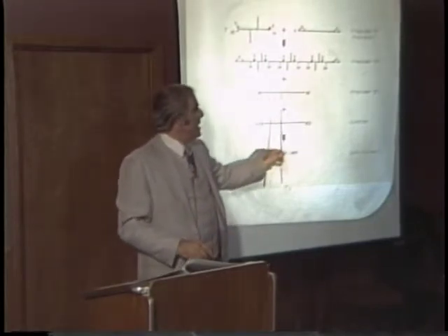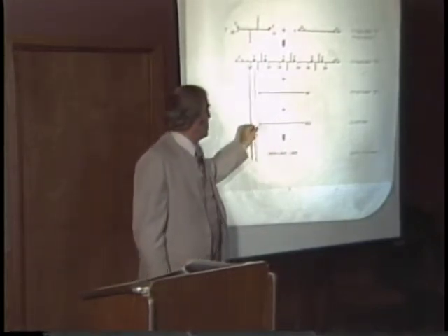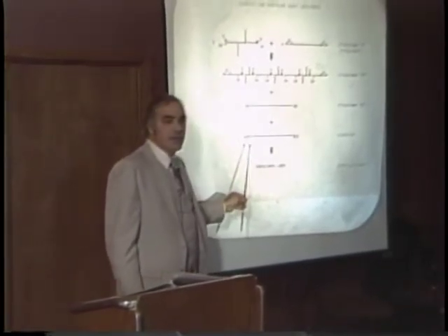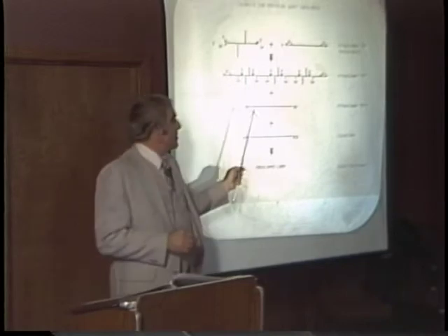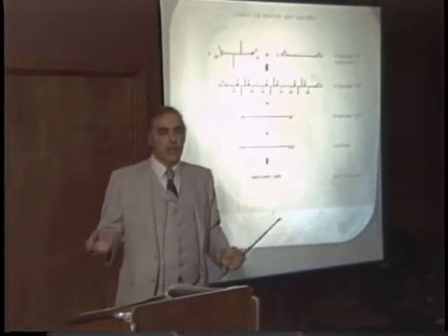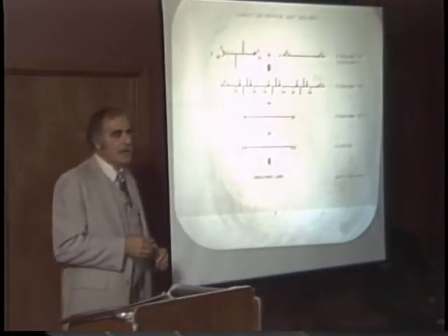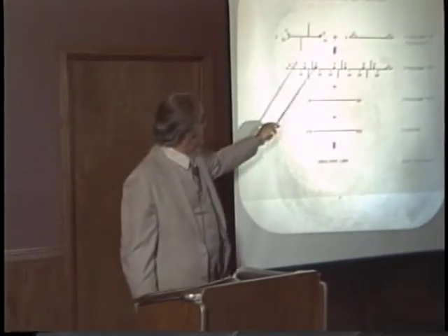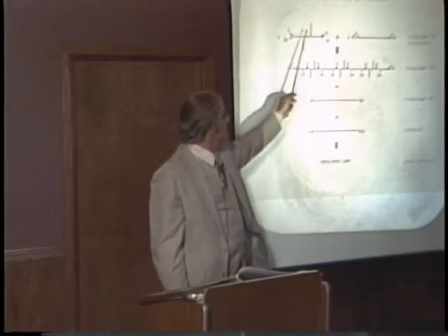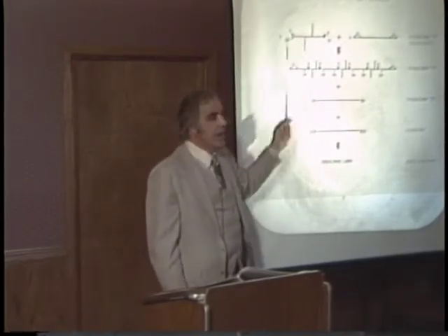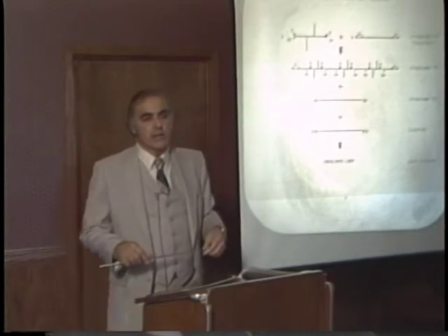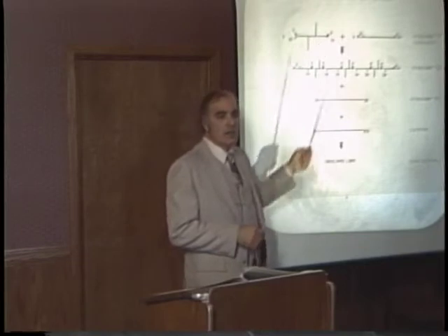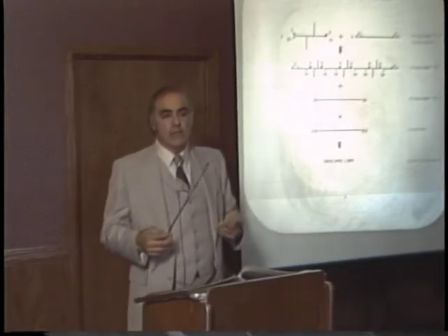But the next thing we do is we take another material and we graft it into each of these hydroxyl groups via the OH and the isocyanate reaction. And this material has a low glass transition temperature, but it's generally highly permeable and not suited in a lot of respects to good bonding. Now the reason we chose this material up here is the dimer acid type of situation. We found that the presence of pendant non-functional groups allows us to get good bonding when we have a very tightly cross-linked matrix.